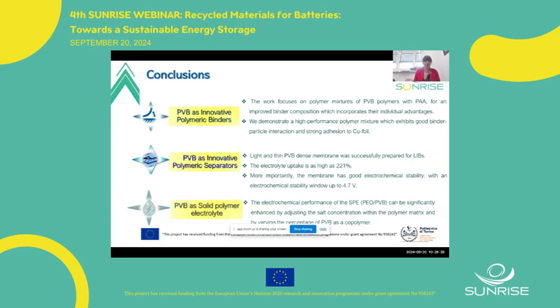Regarding using PVB as a polymeric separator, we could successfully prepare for lithium-ion batteries a light and thin PVB dense membrane, which has a good uptake percentage, ionic conductivity, and is very electrochemically stable. At the end, we also made PVB as a solid polymer electrolyte to avoid using liquid electrolyte due to the problem of explosion and fire, etc.